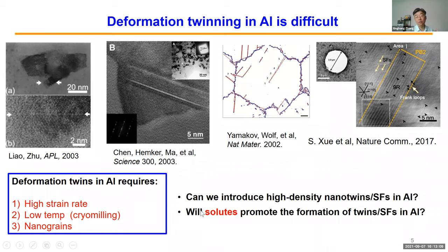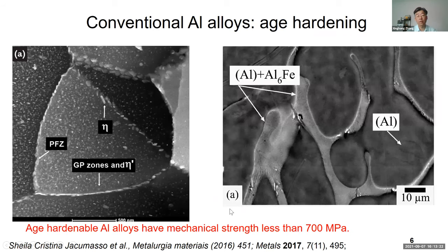And hence we were asking ourselves a question: can we play some tricks to introduce twins in aluminum? Today we're going to mostly focus on using solutes to introduce twins. Before that, if you look at the literature, history told us aluminum alloy has been well studied for centuries. This is a classical age hardening mechanism: introduce precipitates, and then you can get high strength aluminum. Strength is normally less than 700 MPa.